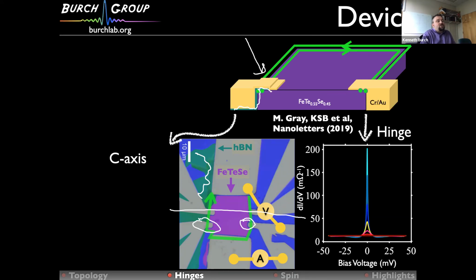Great, okay. So what did we see? The data that you see on your right came from this point contact that touches the hinge. And above Tc it looks totally flat and boring, like a normal ohmic contact. And when we cool down, we see this enormous zero bias peak. I'm going to say 7 Kelvin, though we've since learned that it was probably hotter for reasons I don't have time to go into, but it was definitely below Tc. And the key point is that we see this enormous enhancement, 17 times. So it can't be just standard Andreev reflection, for example.